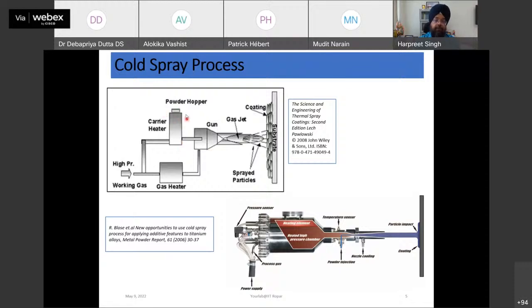Now, we are propelling our powder particles and we are propelling our gas as well, and we heat this gas to some extent. Why do we heat this? This is about thermodynamics, because if you don't heat your gas, when it expands through this nozzle at the throat, there is a sudden expansion, your gas can get cooled and you may face choking or something like that. Another thing is that when you heat the gas, it can achieve supersonic velocities easily, because the velocity can be increased for the lighter gases. So this is a very brief introduction to the cold spray process.